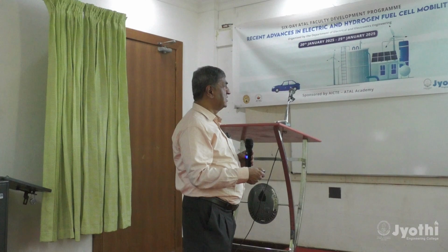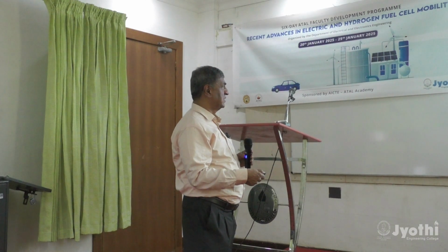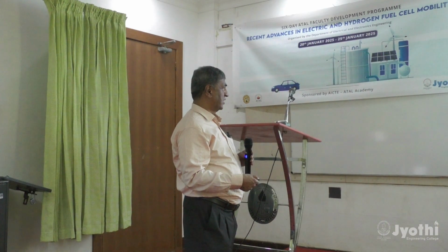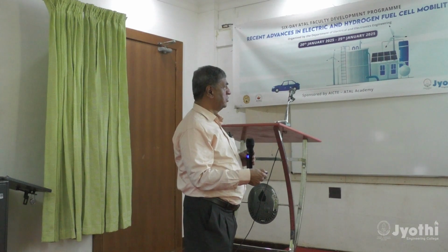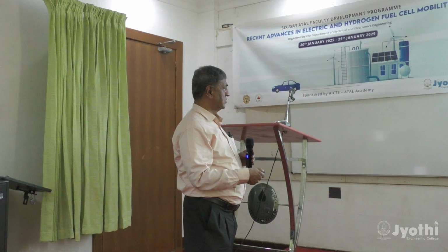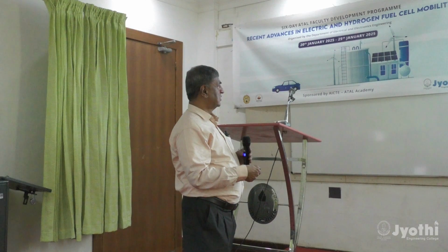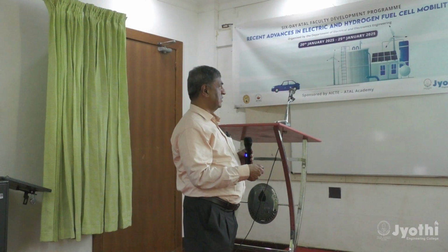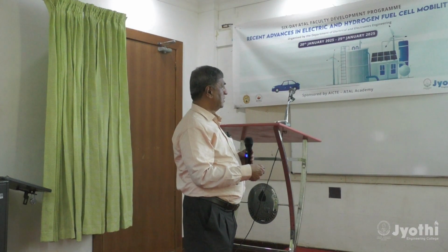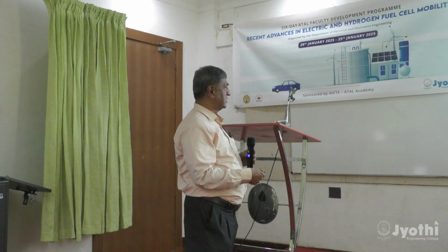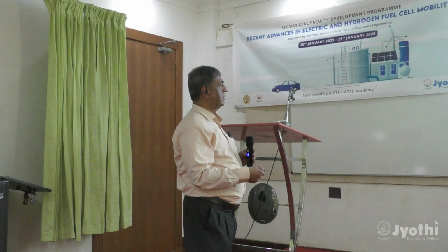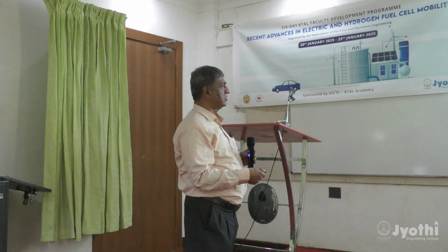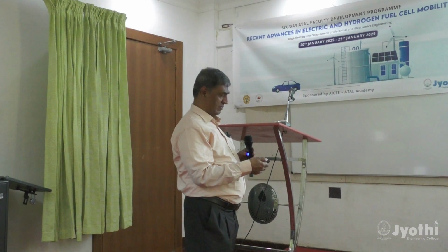The temperatures at which this will take place, depending upon the process, can be different. We primarily produced hydrogen through the first one. This was producing a good amount of hydrogen actually from metal scrap and iron filings which we collected from the workshop, etc. And at a temperature in the range of around 1000 degrees it was produced.